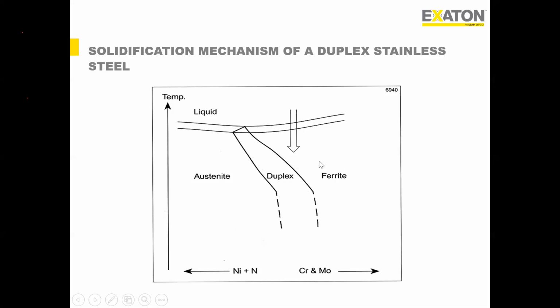On the other hand, if our cooling rate is slow, then we are allowing this liquid weld metal to first form the delta ferrite or ferrite, and it gets enough time to transform into austenite. So in the final product, we may get a lot of austenite and less ferrite. So for our desired microstructure, although it is theoretically 50% ferrite and 50% austenite, depending on the alloy elements as well as the cooling rate, we sometimes can get 30% ferrite, sometimes 50% ferrite, or sometimes even 65-70% ferrite. So this is the role of us as welding engineers, to determine the alloy elements as well as the cooling rate.